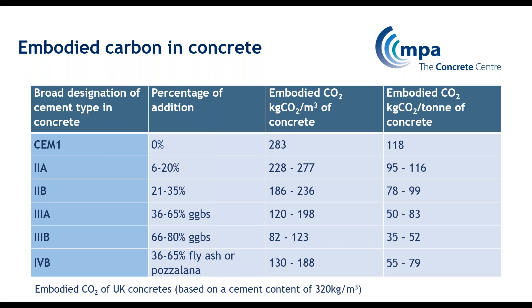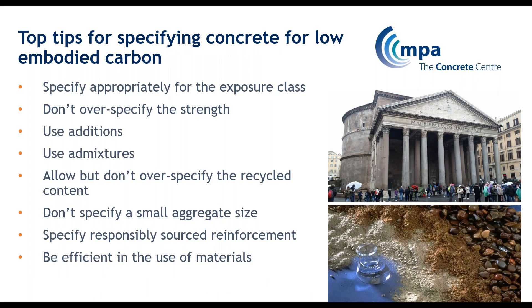The way to reduce embodied carbon in concrete normally starts with looking at the cement you're using, but there are other things to do as well. Make sure you're using the right concrete for the job. Don't over-specify the strength, because the higher the strength, the more cement you need. But you also need to look at the right exposure class to ensure durability. It might not help the embodied carbon in the very short term, but overall you're looking for concrete to be long-lasting. A picture here of the Pantheon in Rome, which is 1,900 years old and is a concrete building — so that's durability for you.